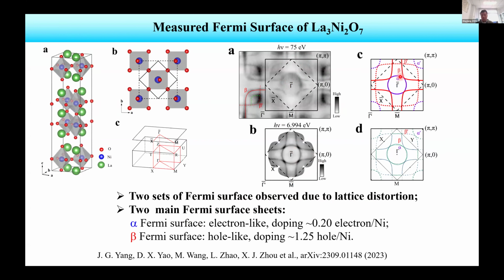One is called alpha. This is the central one, like a circle. This is alpha, it is electron-like, and it corresponds to a doping level of about 0.2 electron per nickel. The second one is the beta Fermi surface. This is the red one. It's hole-like. By counting the Fermi surface area, it corresponds to a doping level of about 1.25 hole per nickel. So we have mainly two Fermi surface sheets observed in 327 at ambient pressure.